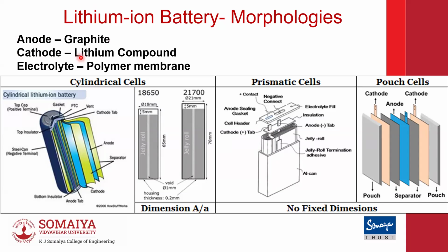The cathode is going to be a lithium compound, preferably a lithium layered oxide. The reason for layering is that the lithium has to move from between the layers to the layers of your graphite. Graphite is anyway a layered material. So the lithium moves in and out. Electrolyte is a polymer membrane, and these are some of the different formats that you have. We have cylindrical, prismatic, pouch. For R&D purposes, people tend to use coin formats also.